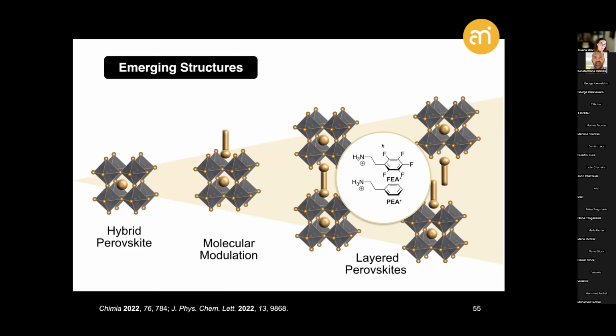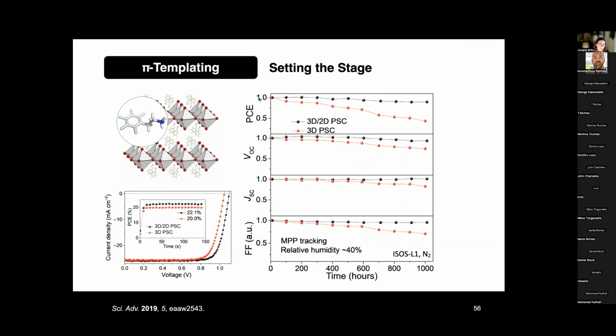In fact, FEA-based systems have already demonstrated the capacity to not only form well-defined two-dimensional Ruddlesden-Popper phases, but also contribute to stabilizing, for instance, formamidinium-rich lead halide or especially lead iodide compositions, as illustrated in one of our earlier collaborative efforts, where these two-dimensional materials were used as overlayer on the formamidinium lead iodide phases, leading to further enhancements in their performances by suppressing some of the defects, but more importantly, their long-term operational stabilities, even in humid environments, which was ascribed to primarily the hydrophobicity of this spacer group that is relevant for moisture resilience, but also achieving more appropriate contacts with the hole transporting materials.